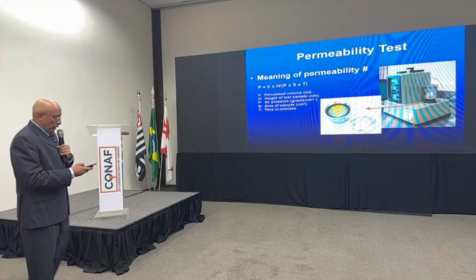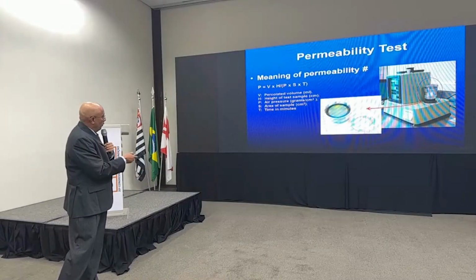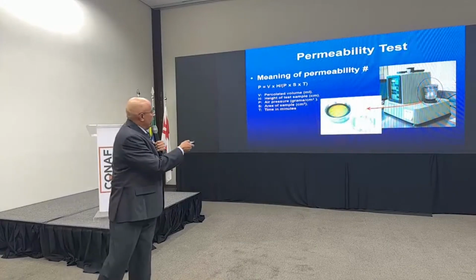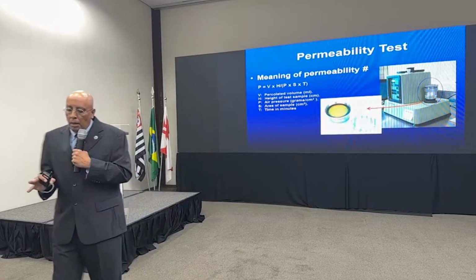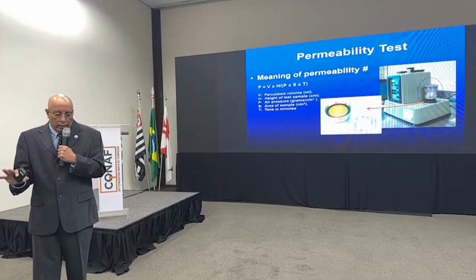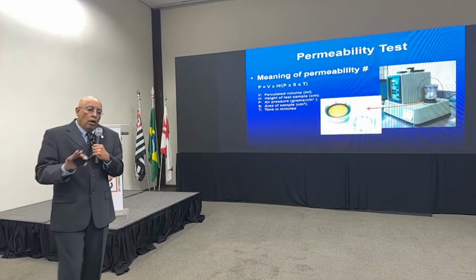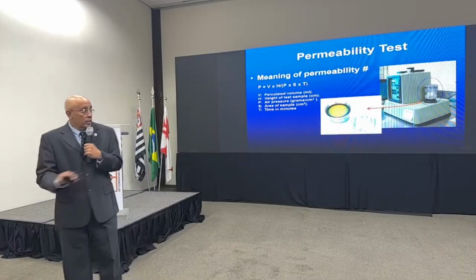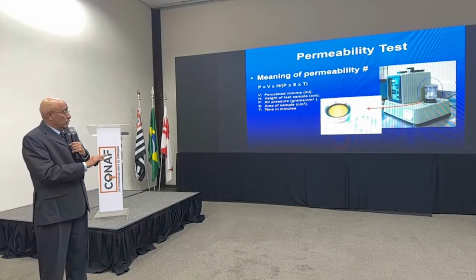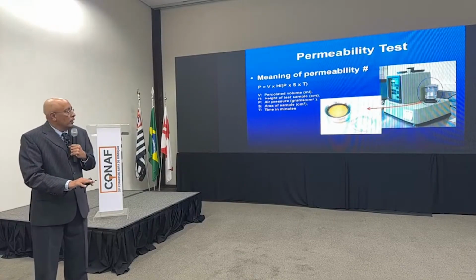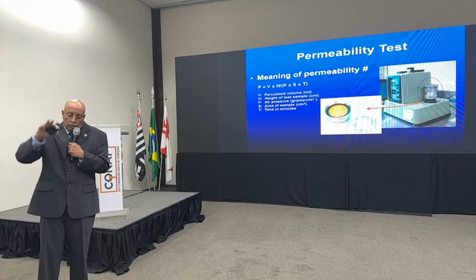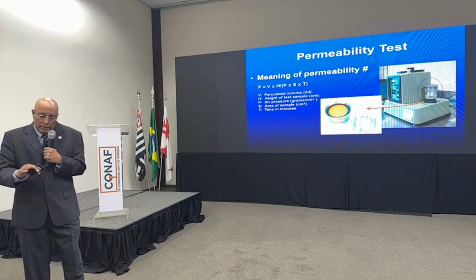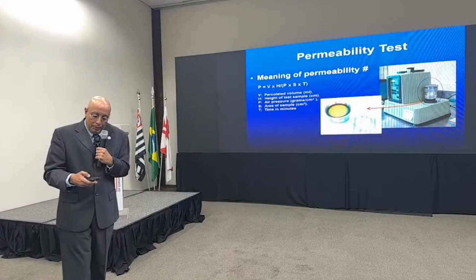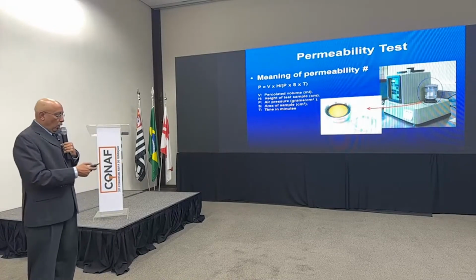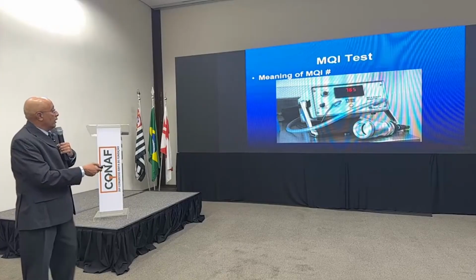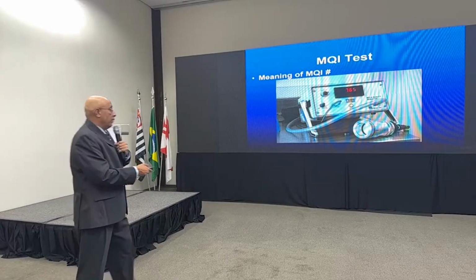The permeability is a long and drawn out formula that the AFS gives a number that is a complex measurement that literally tells us very little. It only tells us how fine or coarse the sand would be, because this test is standard runs at ambient. So it forces 2000 centimeter cube of air through the specimen, and the time ultimately that it takes for that to happen is the permeability number. I will show in a video how we run this test using the MQI modified.